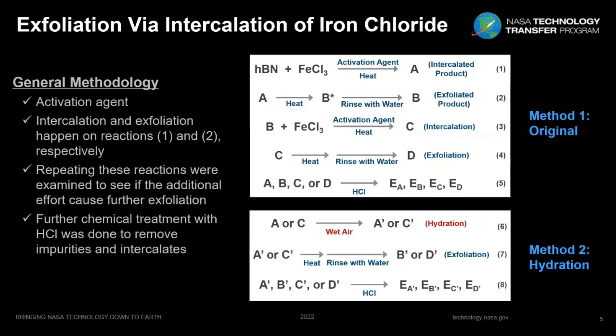So Shinche also developed a second process that is the same one, but after the intercalation process, we do a hydration process in wet air. The intercalated hexagonal boron nitride gets hydrated, and then you exfoliate that product, and that's the second method, the hydration method. And then you can clean the product and obtain white, clean boron nitride at the end.